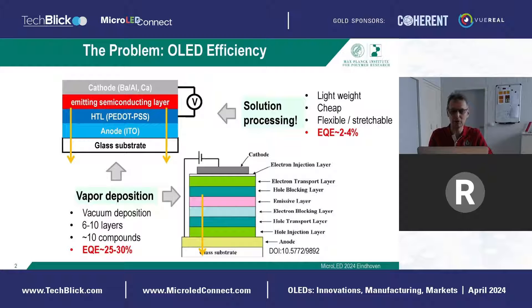However, the problem was efficiency. The simple polymer LED has two organic layers — a hole transport layer of PEDOT:PSS and an emitting polymer — but the efficiencies were very low, with external quantum efficiencies on the order of only a few percent. In parallel, small molecule OLEDs had the advantage that you can stack many layers on top of each other without dissolving the others. Over time, these OLEDs became quite complex with many layers, but also reached very high efficiencies and stabilities — typically EQE is more in the range of 25 to 30 percent.